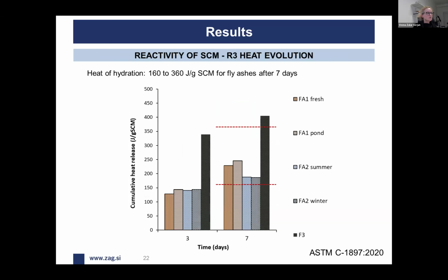Another prescribed procedure for analyzing the hydraulic activity is again connected with the supplementary cementitious materials. You're measuring heat evolution by isothermal calorimetry, and it is the so-called R3 test, which was prescribed by RILEM, according to ASTM C1897. So here you are measuring the heat of hydration in a mix of different chemicals, where you are adding your material of interest. And here the characteristics of FA3 ash, which was shown to be promising in the measuring of the strength values, show even greater potential.